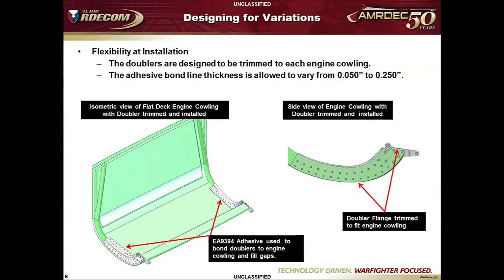We've tested these. A brand new engine cowling from the factory will fail at about 2,100 pounds. We took a brand new engine cowling and induced damage in two spots on there, right at that critical area just past the hinge. We made a 1/4 inch wide, 1/2 inch deep cut. Then we put our doublers on there. We're breaking cowlings at about 2,700 pounds. However, it's not our doubler that's failing, it's the aluminum fitting. The aluminum fitting will only go to about 2,700 pounds. So the big question mark is how much load can our doubler take?